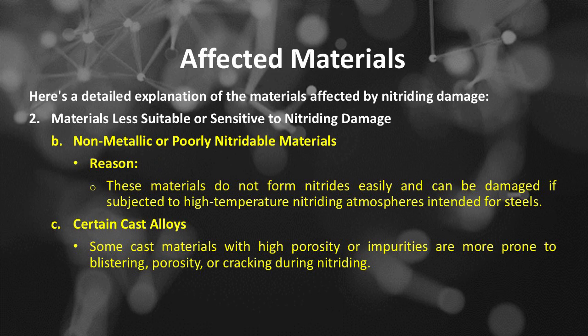Nonmetallic or poorly nitridable materials do not form nitrides easily and can be damaged if subjected to high-temperature nitriding atmospheres intended for steels. Number C, certain cast alloys. Some cast materials with high porosity or impurities are more prone to blistering, porosity, or cracking during nitriding.